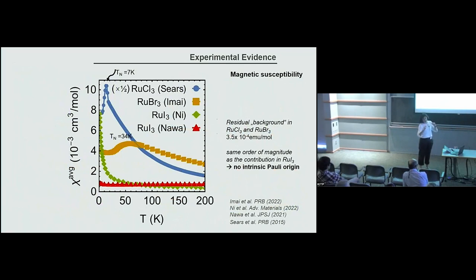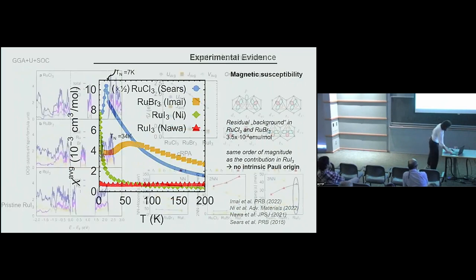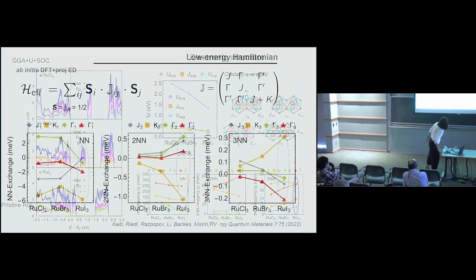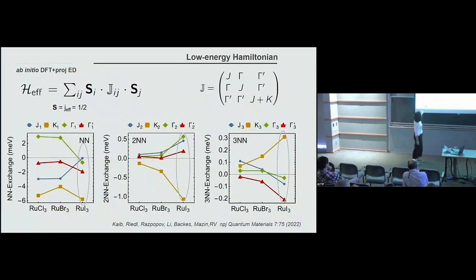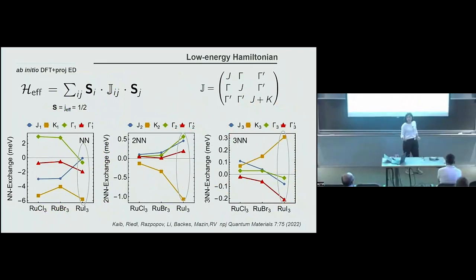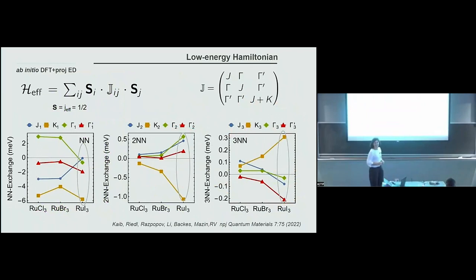So which is the driver there? Is there a clear driver, what interaction is driving the zigzag order? The driver, let me see it here. If you look at the ruthenium bromine, you see that there are all these interactions here that are not there in the chloride. So these start to be important in the bromine. I was looking at that one, and I thought, oh, the J3 has gone down, and J3 was the one I thought was responsible for the zigzag, so I thought it ought to be less ordered, but it's actually more ordered. We have to disentangle a little bit better, but we find that this K3 here starts to play a role.